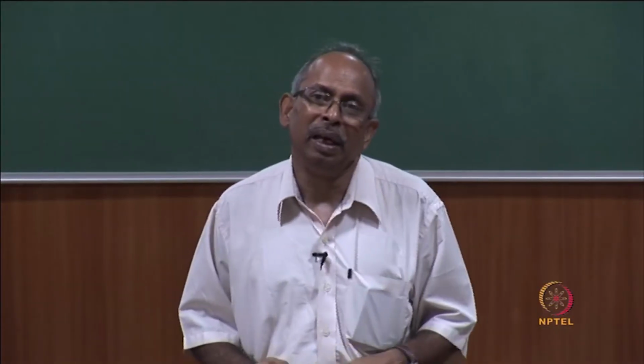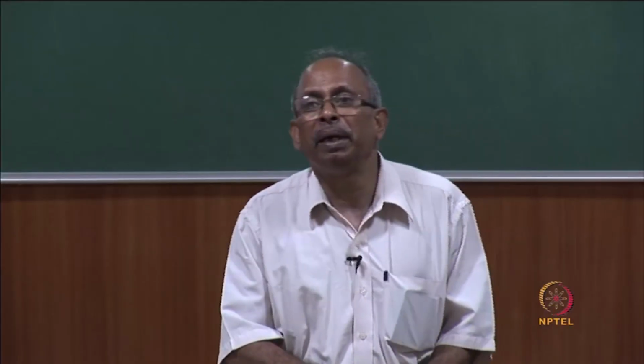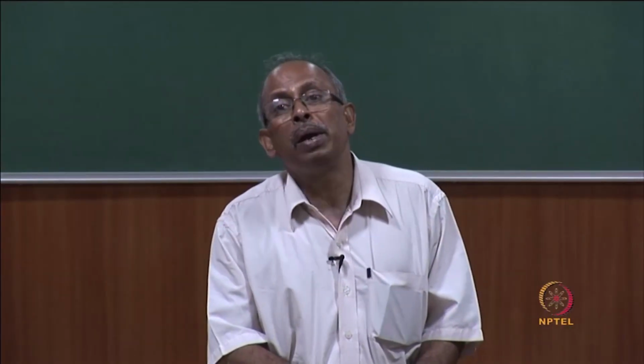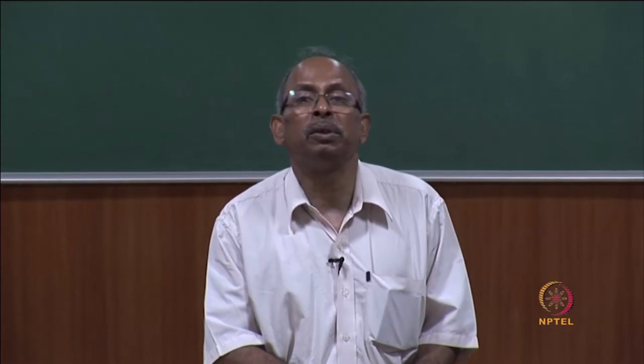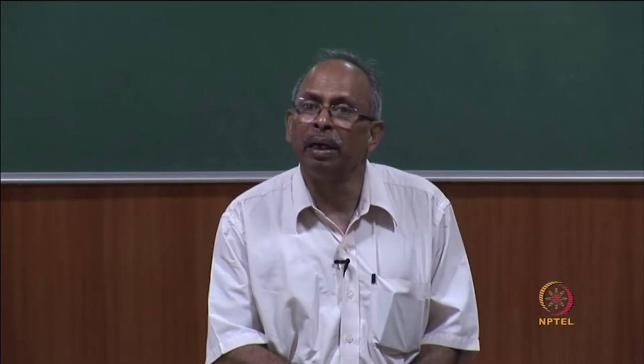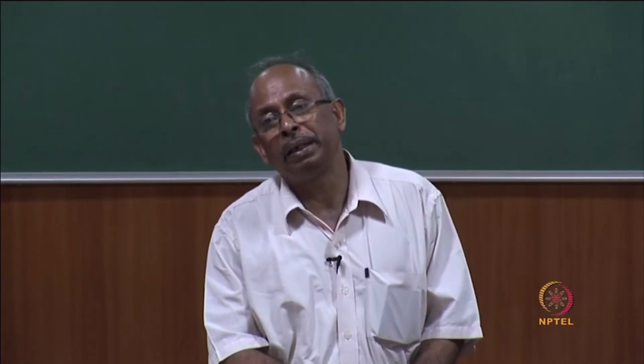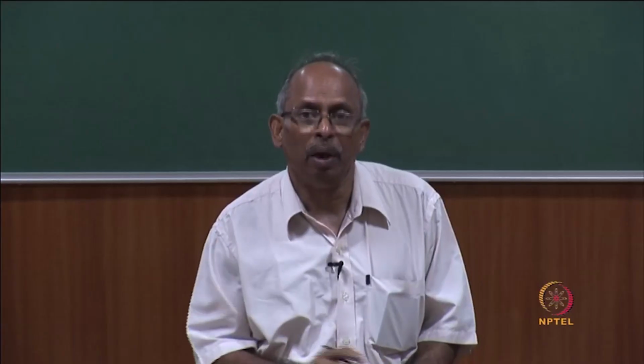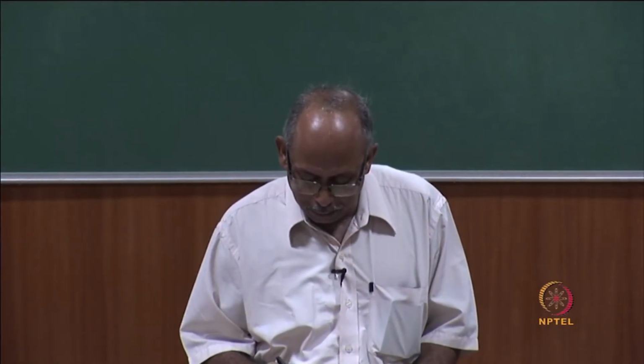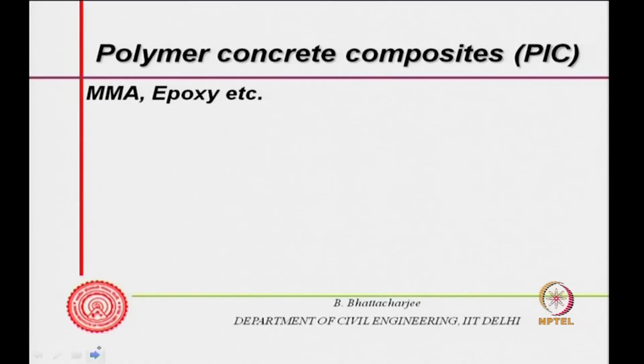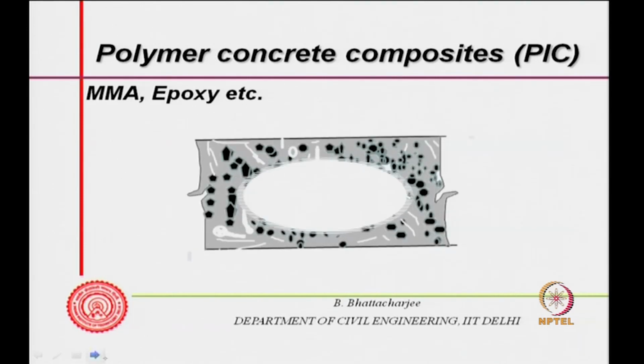Polymer impregnation actually did a very good job there, because once you put that, your wearing coat lasts much longer, its abrasion resistance increased, durability increased, and therefore it will also protect the inside structural element longer. So, this was polymer impregnated concrete. Methyl methacrylate, epoxy, many of those polymers have been used for this purpose. So, that is what we showed earlier.